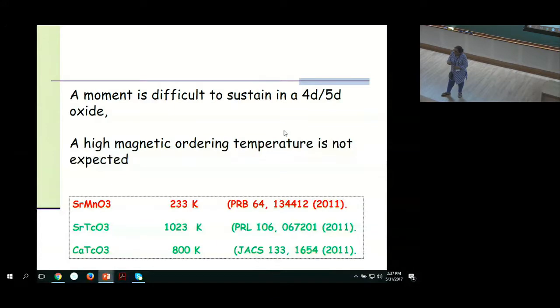I'm sticking to half filling of the band, where, because you have the T2g half filling, the spin orbit is effectively L equal to 0. So there's no effect of the spin orbit at half filling. If you go back to the periodic table and look at these elements, technetium has a formal d electron configuration of d3 in these compounds.